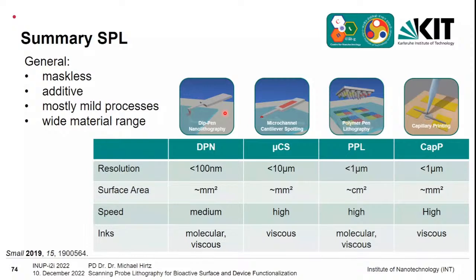What we can achieve in writing is a little bit different, because this again depends a lot on what kind of ink you use. If you have, for example, thiols on gold, as I showed you, this can give you a fairly high resolution, around 50 nanometer. But if you have an ink that's more prone to spread on the surface, and also if the surface, for example, is very hydrophilic and so high energy and likes to attract the ink that you deposit, then this can go up. For example, the lipid resolution with the phospholipids is around 100 nanometer. And if you want to deposit, let's say, a water-based ink, then maybe